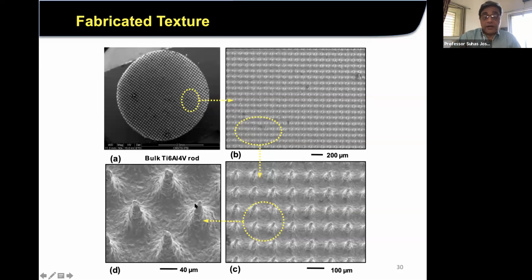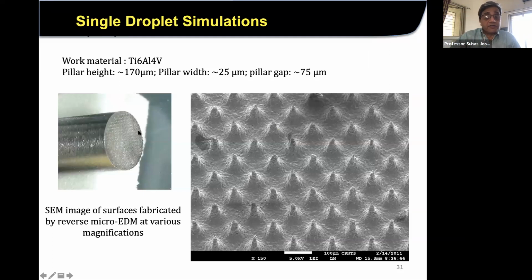You can see now this is a rod which has these kinds of projections, and the pillar height is about 170 microns, width is 25 microns, and the gap between them is 75 microns. So they're fairly close-by pillars. Of course, they depend on how well you can make the holes in the electrode itself.